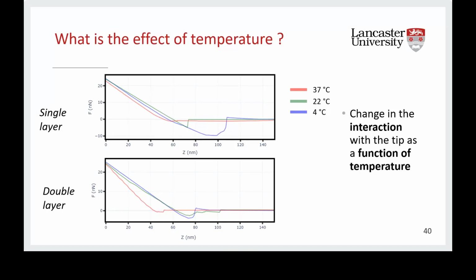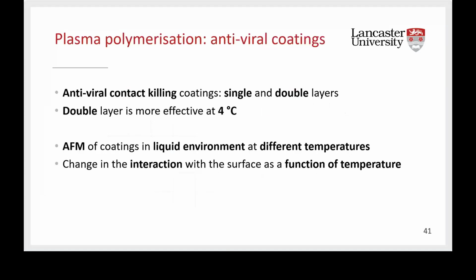We notice the same happens in the double layer, but we saw also some change in the mechanical response. And we are trying to replicate these experiments to see if these results are consistent. But the key point is that with the colloidal probe AFM, we can sense the change of interaction as a function of temperature in these coatings.